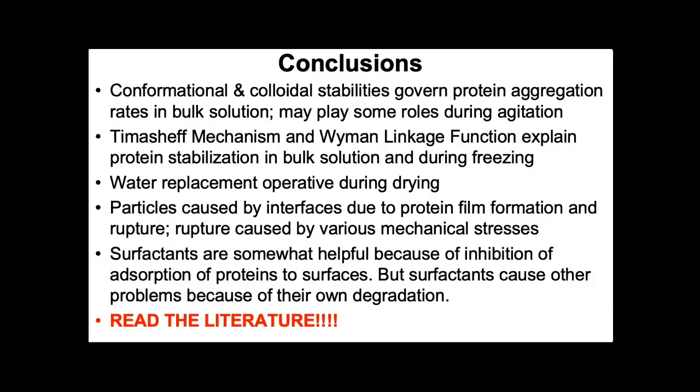Okay, let me conclude and say that we know in bulk solution that both conformational and colloidal stability are important for governing aggregation of proteins. And stabilization by additives can depend on specific ligand binding through the Wyman linkage function, for example, or nonspecific stabilization through the Timasheff mechanism. This also applies during freezing. Whereas during drying, as we strip the hydration shell off the protein, water replacement is the mechanism.